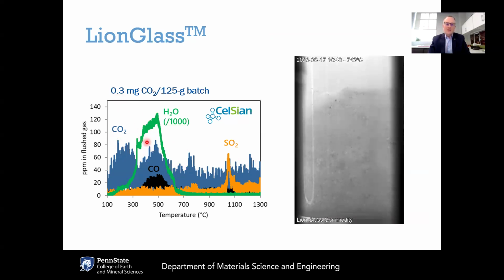The major gas that gets released from LionGlass melting is water vapor. This is the water vapor concentration divided by 1,000. If you integrate this, it's something like 8 grams of water vapor that gets released. So we're trading in something that is environmentally harmful, CO2, for something that is environmentally neutral, H2O. This also includes a bit of sodium sulfate as a fining agent, and that's where the SO2 blisters come from.